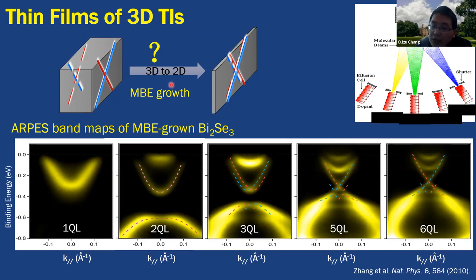So first, we use MBE to grow the thin film of 3D topological insulator. This is the ARPES band map of the MBE grown bismuth selenide on the graphene substrate. We can see that from 1 quintuple layer to 6 quintuple layer, where 1 quintuple layer is just 1 nanometer of bismuth selenide, we can see very good quantum well states here. And these quantum well states indicate a film with uniform thickness. And we can see that when the film thickness is below 6 quintuple layers, there is a gap opening. This gap opening is just due to the top and bottom surface hybridization.